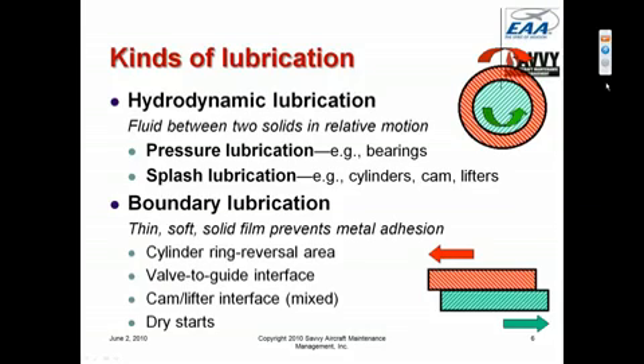The way those surfaces get hydrodynamic lubrication is by what's called splash lubrication, where large quantities of oil in the form of a mist is directed against those surfaces and provides the lubricant. For example, cylinder walls are lubricated because large quantities of oil are extruded out the main crankshaft bearings and the large rod end bearings, and because the crankshaft is spinning at a high speed, the oil that's extruded out of those bearings gets flung in every direction in the form of a very dense oil mist.